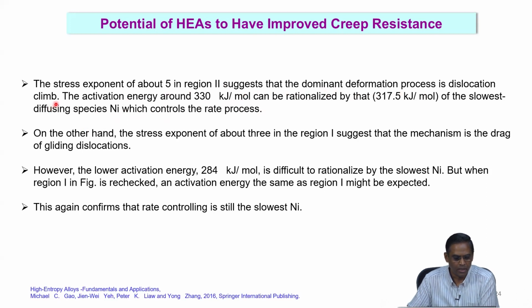On the other hand, the stress exponent of about 3 in region 1 suggests that the mechanism is drag of gliding dislocations. However, the lower activation energy of 284 kilojoule per mole is difficult to rationalize by the slowest nickel, but when region 1 in the figure is rechecked, an activation energy the same as region I might be expected. This again confirms that the rate controlling species is still the slowest, nickel.